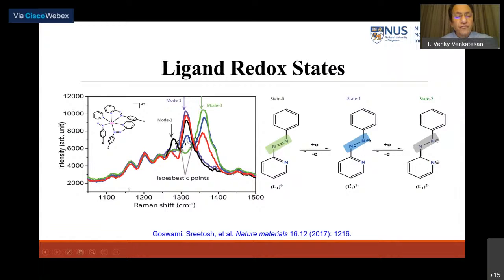Okay, here are 3 different redox states the molecule is in, and this is the Raman spectrum. And what you see here is there are a lot of molecular bands which don't change at all when I change the redox state. However, there are 3 modes, marked mode 0, mode 1, mode 2. They dramatically change in intensity when the redox state is changed. State 0 corresponds to the azo group in its neutral state, whereas state 1 is one electron reduced, and state 2 is two electron reduced. So now by looking at the Raman spectrum, you know exactly the redox state of the molecule.